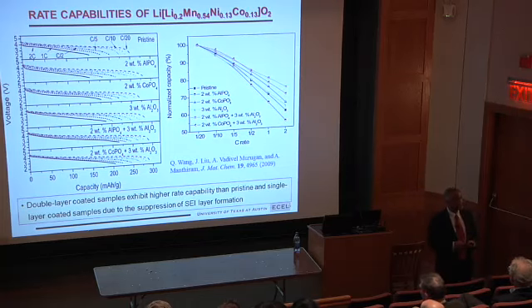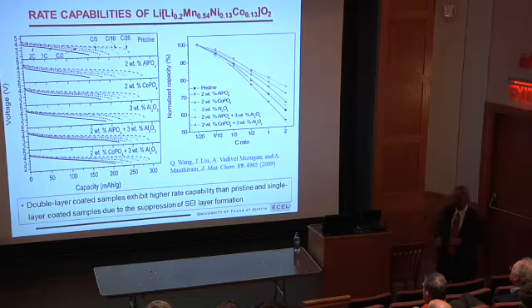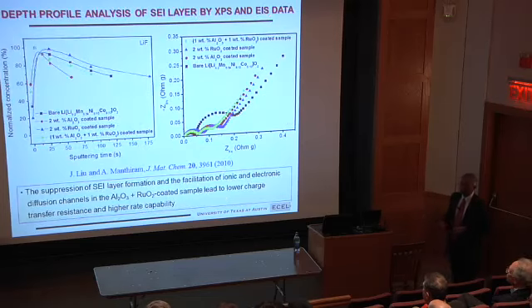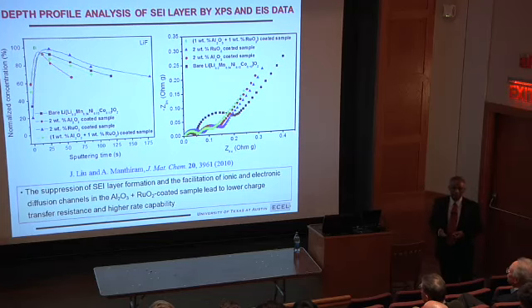That's because when you coat with aluminum oxide or aluminum phosphate, you suppress this aggressive reaction of the transition metal ions in the cathode with the electrolyte. Basically, you decrease the SEI layer formation at higher voltage, so rate capability goes up. We have done some XPS. The black one is uncoated material. The red and green ones are coated material. You do see less concentration of LiF. That means you have a less thick SEI layer.